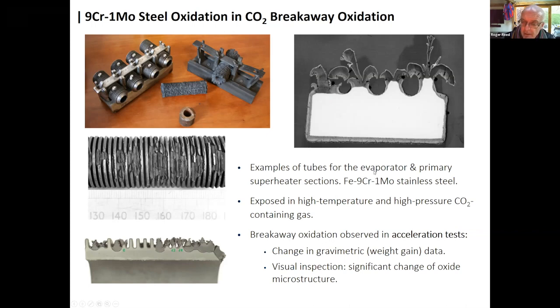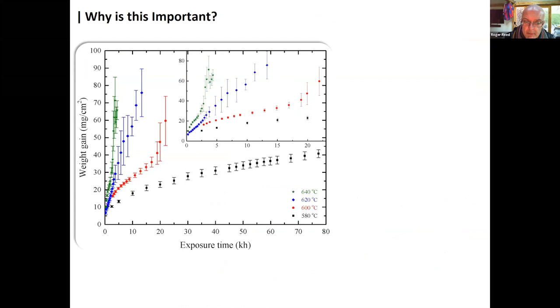Now, I should say that so far there have never been any examples of failure of these pipes by breakaway oxidation. But of course, that possibility exists. So the likes of EDF Energy conduct high temperature or higher temperature tests to try to anticipate whether the plant is safe or not. And they do this by using gravimetric analysis to measure the weight gain, and visual inspection to look at whether there is a change in the oxide microstructure. So this is what we have been working on.